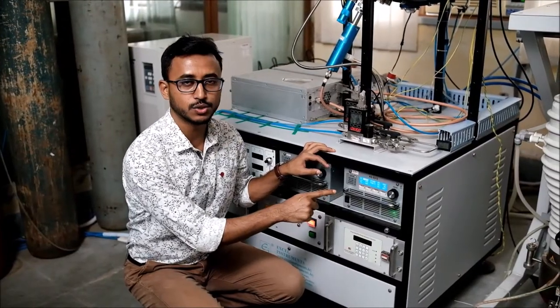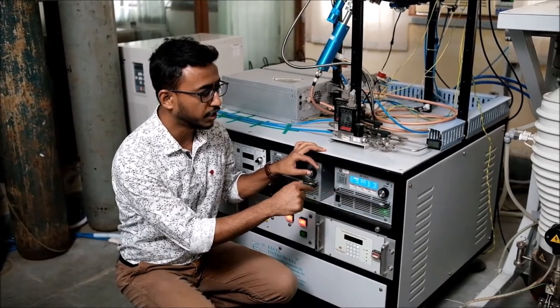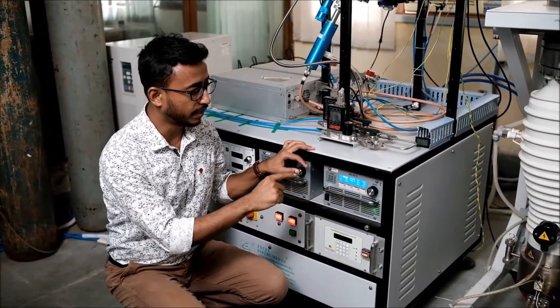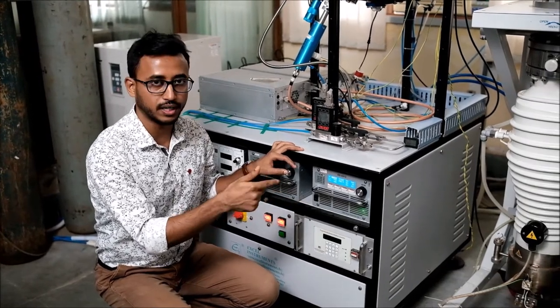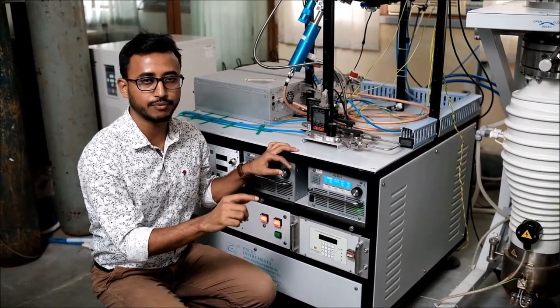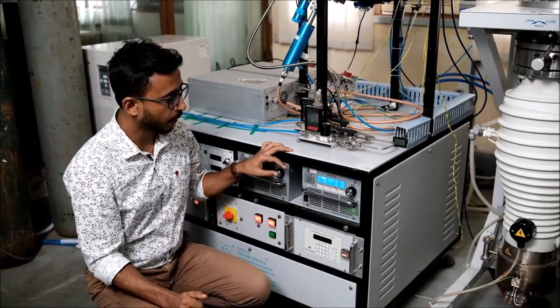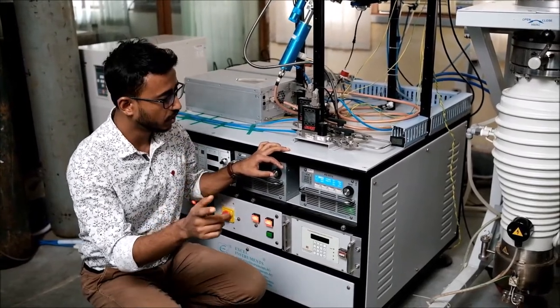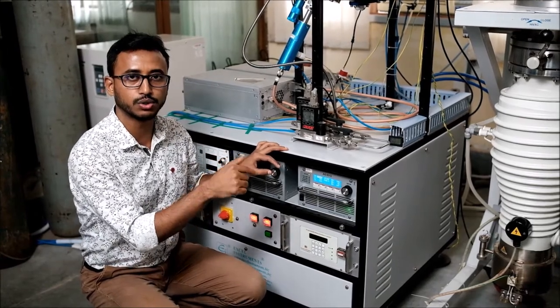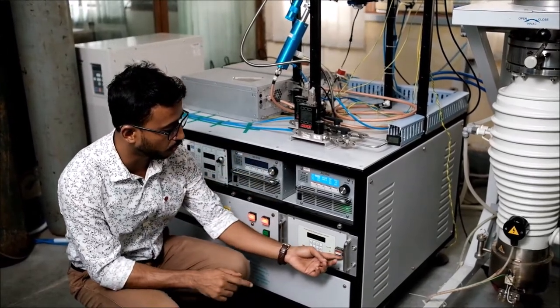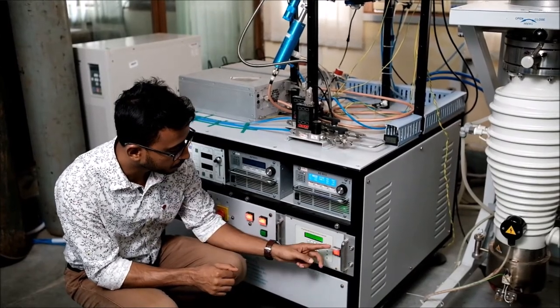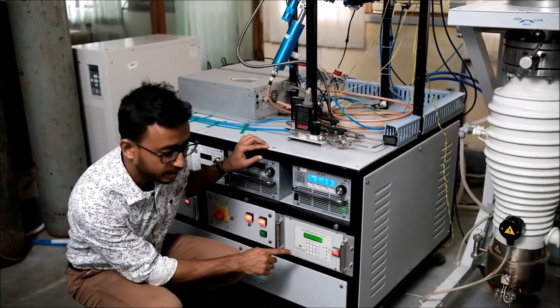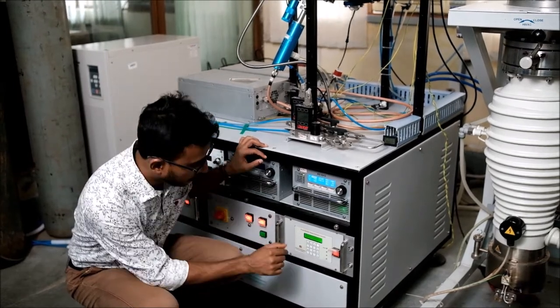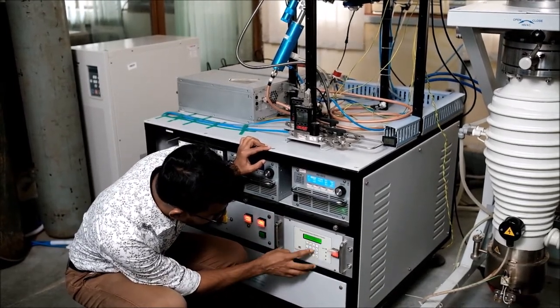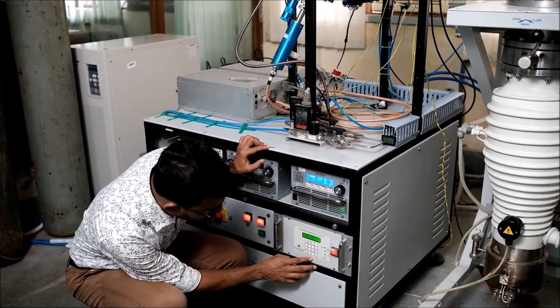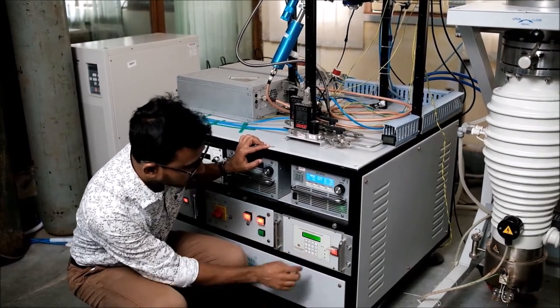So now I have reached 50 watt of power, and it took around 10 minutes. And by the time I reached the power, the pre-sputtering is also done. I ran this sputter for 10 minutes to clean up the target surface. So now I am ready for my actual deposition. I want to rotate the substrate holder throughout the deposition, so I turn on the rotation of the substrate holder now. I will set 20 RPM of rotation. So click on the RPM, set it to 20, enter.